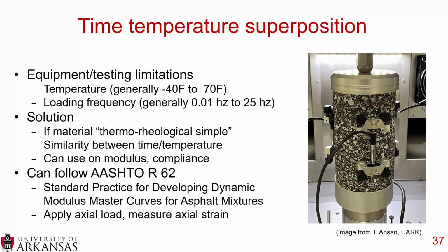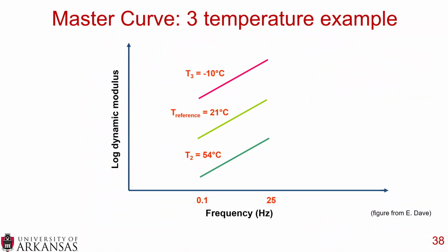But what is this time-temperature superposition? How does it work? If we're constrained by 0.01 to 25 Hertz, and we're constrained by temperature, this is what we do. We run multiple tests at multiple temperatures. We put our sample in the environmental chamber at minus 10 degrees Celsius, and we run the dynamic modulus from 0.1 Hertz all the way up to 25 Hertz. With that same sample, we heat it up to 21 degrees Celsius and run it from 0.1 to 25 Hertz. With that same sample, we heat it up to T2, 54 degrees Celsius, and run it at 0.1 to 25 Hertz.